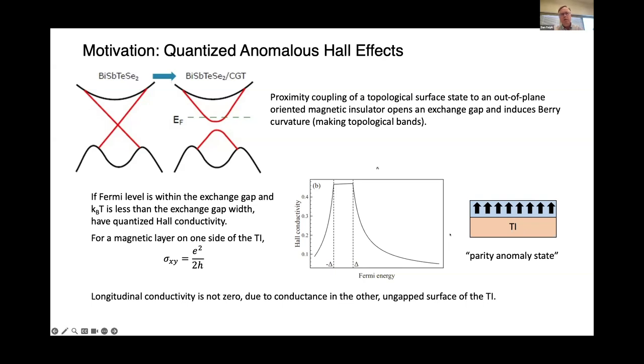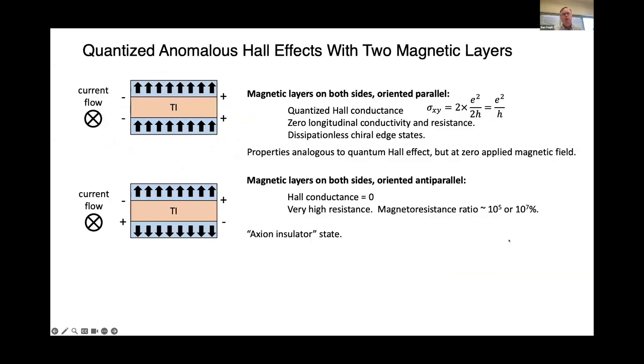It's a bit unusual in terms of quantized Hall effects in that it doesn't have 0 longitudinal conductivity, because the bottom surface of the topological insulator isn't gapped. You still have non-zero longitudinal conductivity there. So these are the sort of structures our group has been making so far. You can also go on and try to gap both surfaces of the topological surface state. And all 3 of these states have been made with magnetically doped topological insulators.